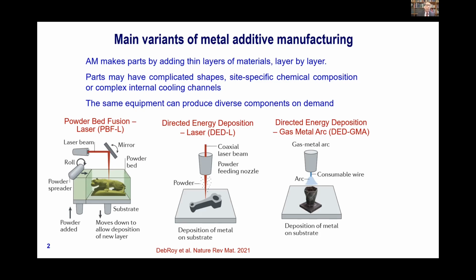Powder bed fusion is where we prepare this intricate part. I'm showing here the Nittany lion, which is a mascot for Penn State. And we are using here a laser beam. We supply a very thin layer of powder, sometimes thinner than a human hair, to make this intricate part layer by layer. Sometimes we supply the powder coaxial through the laser beam and make a powder on a substrate. Or when we need very high productivity, we make use of a gas metal arc heat source, and we supply consumable wire to make large parts quickly using a process which is like a multi-layer welding process.